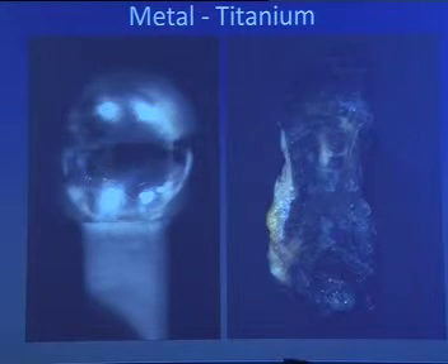Moving on to metal, this was a case that we received recently, and here you see that again the femoral head, it's completely burnished, eroded in this region. And here you see the synovium looks very different from what I just showed you. It's absolutely black. It's not gray-black or red-brown as you would see in hemorrhage, such as post-traumatic hemophilia, hemochromatosis, but this is a characteristic appearance of what we see in patients with metal implants, and particularly titanium, not so much with cobalt, chrome, stainless steel, but with titanium.